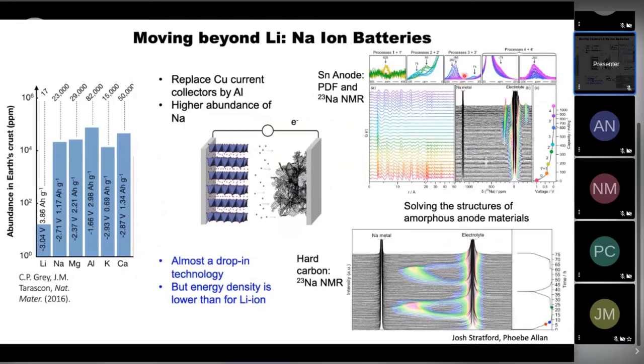We're also interested in sodium ion batteries. I talked about the issue of resources. And so one obvious way of moving beyond lithium is to replace the lithium by sodium, which is much more abundant. And it's almost a sort of drop-in technology where you can use the same approaches and almost the same electrolytes for lithium as in sodium, but you can reduce cost because of the higher natural abundance. And you can also replace the copper current collector by aluminium. One of the problems, though, is that you can't insert sodium into graphite.